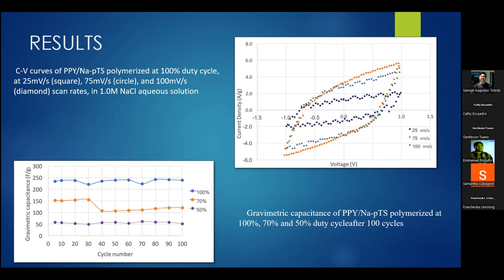So what we did also is to measure the CV plots at different scan rates. So there are three: 100 millivolt per second, which is faster, 75 millivolt per second, and then 25 millivolt per second. So 25 millivolt per second takes longer, so the charging is slower. Consistent with other published results, the measured specific capacitance at 25 millivolt per second scan rate is higher than those calculated at higher scan rates.